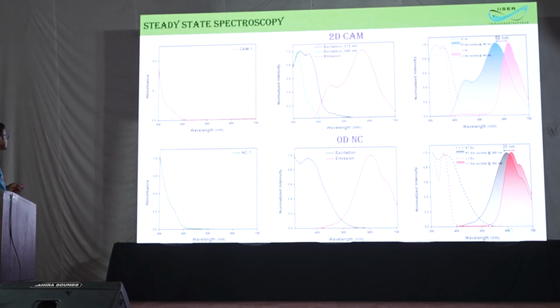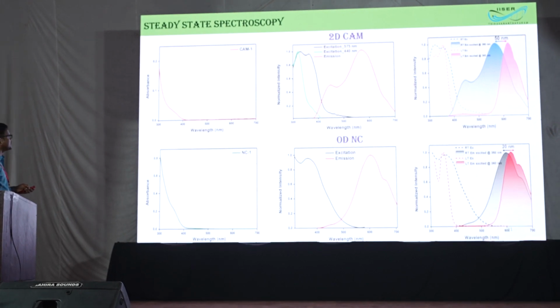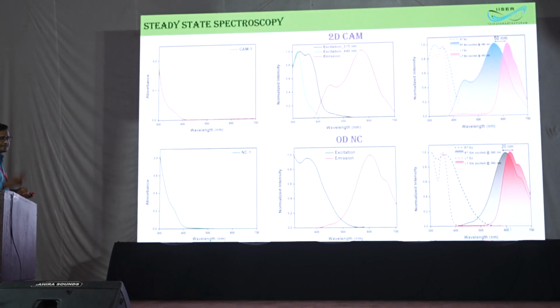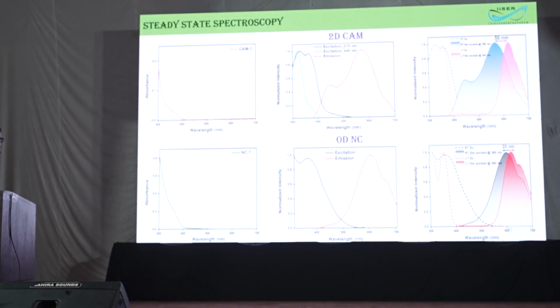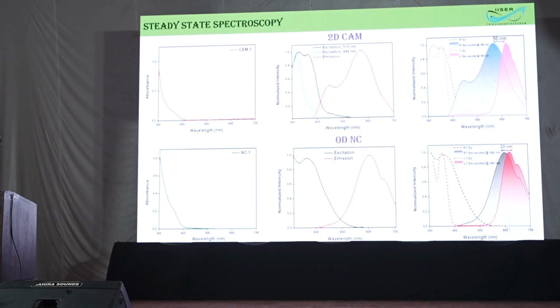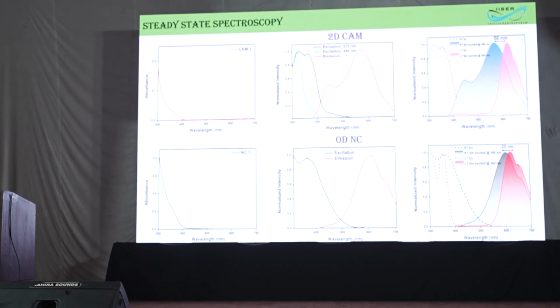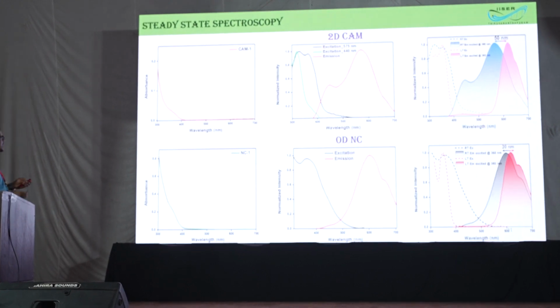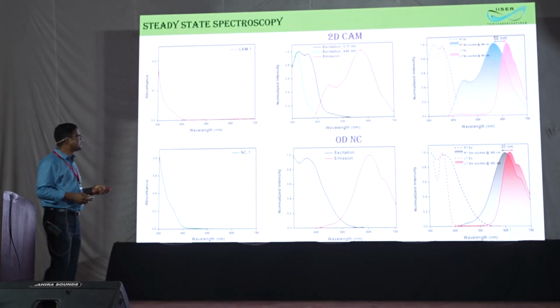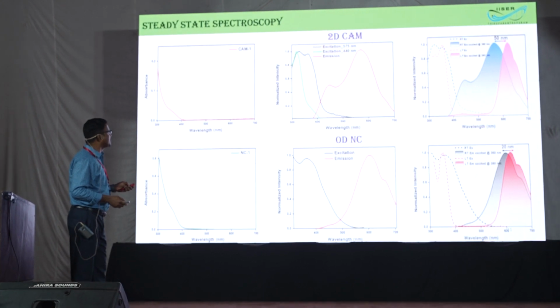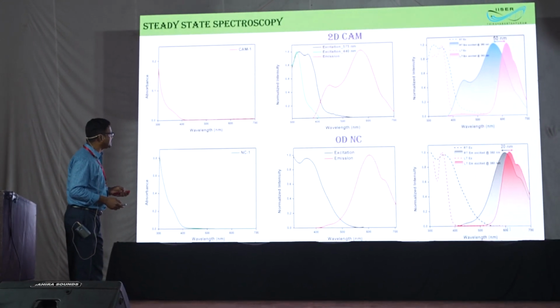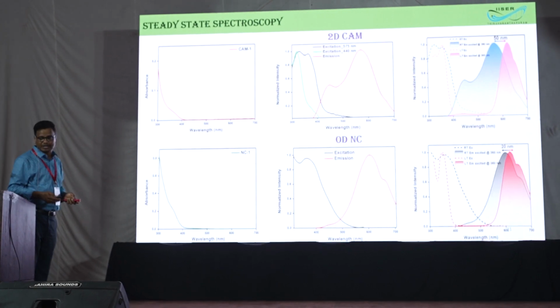We studied the optical properties in the solid state. We can see the solid-state UV absorption and the photoluminescence at room temperature; around 600 nanometer this peak is coming from the linker. Most of the organic molecular cluster shows this peak, so for simplicity you can ignore it, but these other peaks originate from the Ag12 cluster. Now we have done a temperature dependent study. For the two-dimensional structure there is a shift of 50 nanometer, and for the molecular clusters it is 20 nanometer.